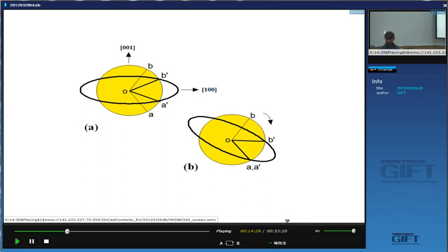So the Bain orientation is altered into the experimentally observed orientation relationship by the rotation that is required to generate an invariant plane strain, invariant line strain. Okay? So exactly the rotation by theta, by this angle here, required to convert the Bain strain into a rigid body rotation predicts the experimentally observed irrational orientation relationship.